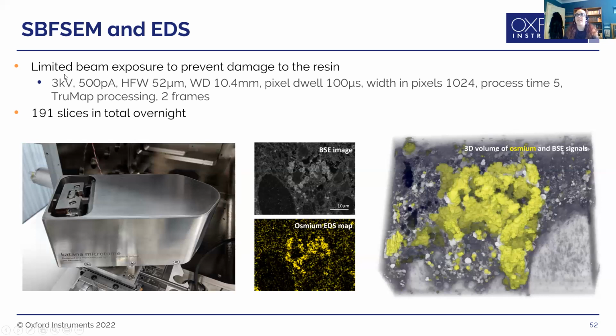So this was collected at 3 kV, and we collected almost 200 slices overnight. This was just 2 frames, so we didn't have very long. If you expose the resin block to multiple sweeps of the beam, it softens the resin in the same way, so you get a distortion of your ultrastructure. So we only exposed it to 3 sweeps of the beam. 1 sweep was collecting the backscatter data, and the subsequent 2 frames were the EDS maps.